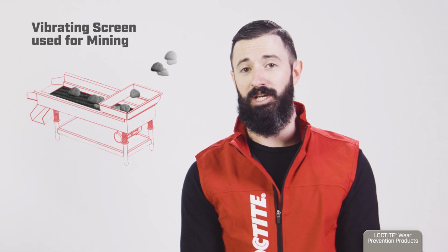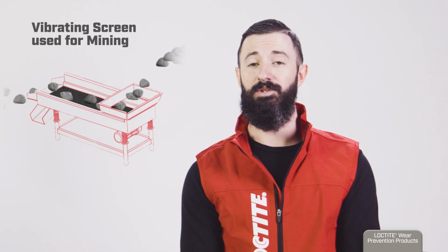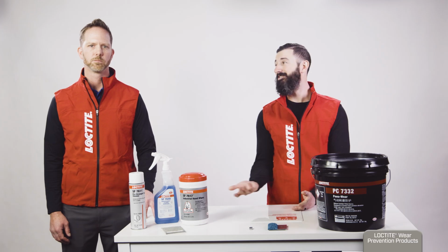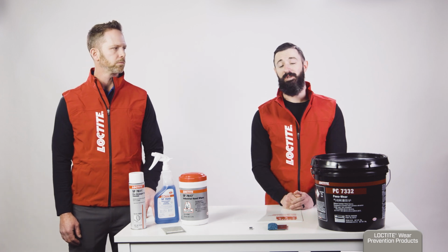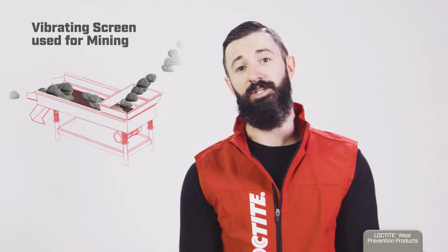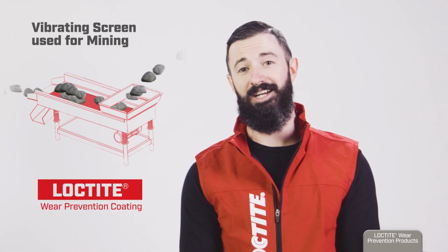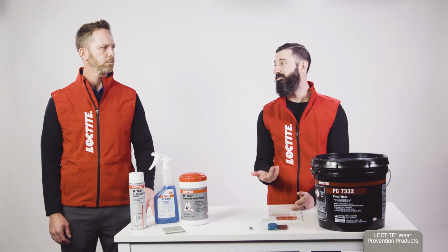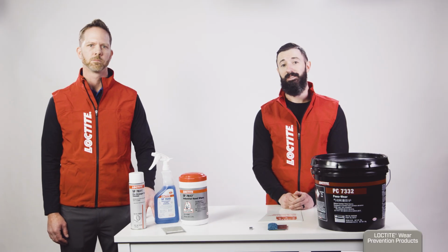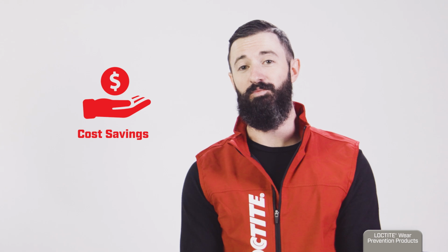Recently we had this application at a customer site where they were using a competitor material that wasn't even lasting 5 days. When we came in with our coating, I applied a coating to their vibrating screen lip, and it actually lasted 3.5 weeks before they needed a recoat on it. That was a significant savings and improvement for them.